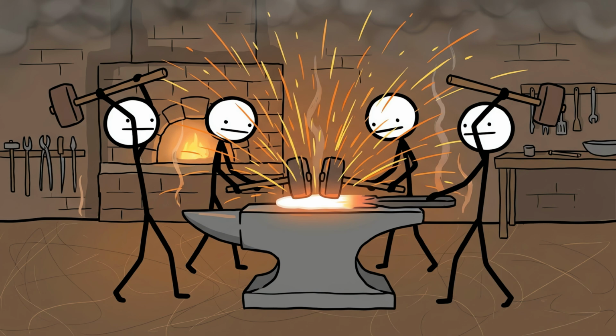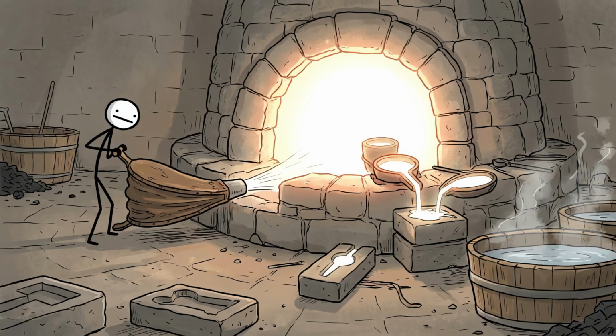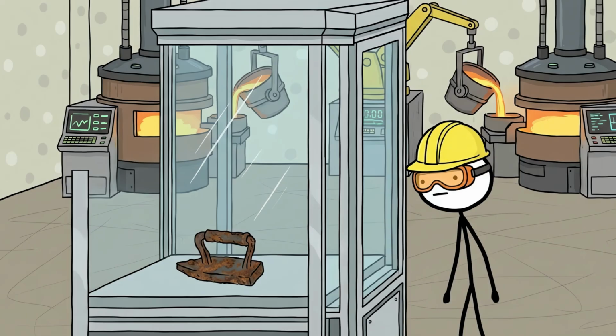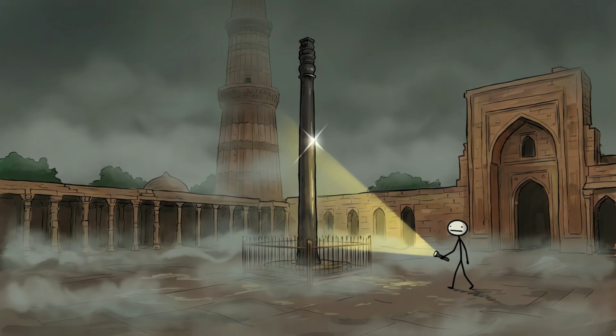The pillar was forged using forge welding, heating and hammering together over 100 kilograms of wrought iron pieces at a time. This required maintaining a temperature of 1200 degrees Celsius or higher across the entire mass during forging. Difficult without modern furnaces. Metallurgical analysis shows no significant corrosion, even in cross-sections. Despite Delhi's monsoon climate, 80% humidity for months annually, the iron remains pristine.